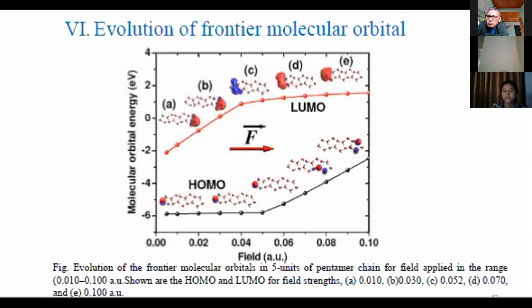The LUMO slowly migrates towards the other end of the cluster. Whereas at the same field, the HOMO almost remains constant, so the gap increases, and then again from this particular field, that is the threshold field, it starts shifting towards the other end, and its energy increases, and thereby again there is the closure of the HOMO-LUMO gap. This is how we account for the peculiar behavior of the increasing and decreasing of the HOMO-LUMO gap.